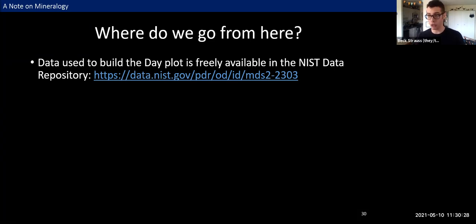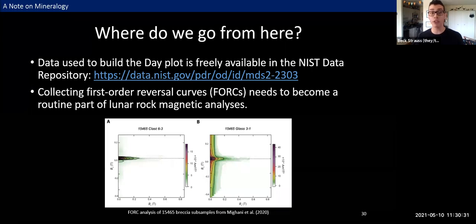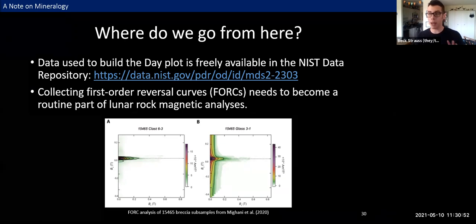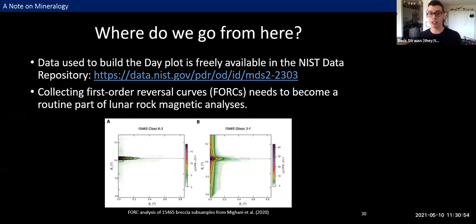I also want to encourage our research community to collect more first-order reversal curves and make them a routine part of lunar magnetic analyses, just like we do for terrestrial analyses. First-order reversal curves essentially fill in the empty space in a hysteresis loop, and they're able to give us a lot more information about different populations of grains and the interactions between them, as well as information about potential anisotropies. Now, something like half the data on that Day plot was collected before this technique was even invented. So this isn't just about future studies of samples that have never been analyzed before, but also about taking care in how we revisit these kinds of archival collections.